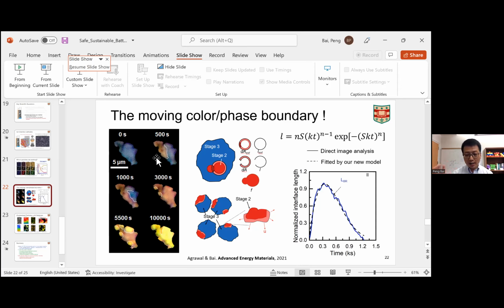That means these particles, even if they're identical, still need to compete for the chance to nucleate. Once one particle got nucleated and this new color starts to sweep across the particle, the other particles have to wait. Okay, this really needs a lot of explanation, but basically, if you're really interested in this, you have to understand the thermodynamics of the material, which later, if you come to WashU, I can teach in the material science course for you. But generally, the majority in this field would believe the structural reasons, non-uniform distribution of the particles, particle size, particle shape, and the contact with different materials in the environment, could be the reason for their random reaction.